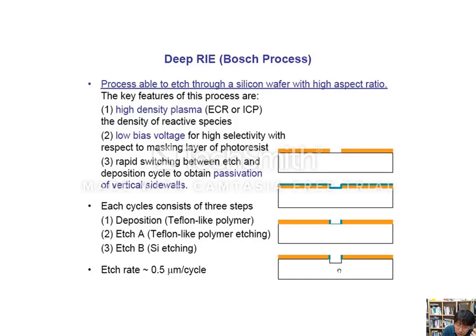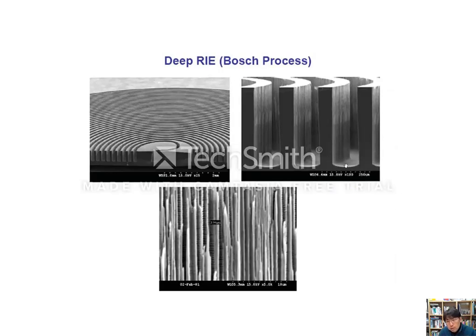So for each cycle, you can reach about 0.5 micron. So when you want to get through almost 500 microns, you have about 1,000 cycles to reach the other side of the wafer. Okay, so that's how they look. You see this very high aspect ratio structure, like a GC application, gas chromatography application. You see the dimension over here from here to here is 250 micron. So the width of the wall is probably somewhere between 50 to 100 micron, but the depth is maybe about 8 or 9 times larger than the width of the wall, right? So that's the high aspect ratio.